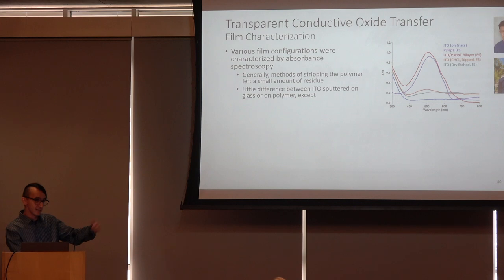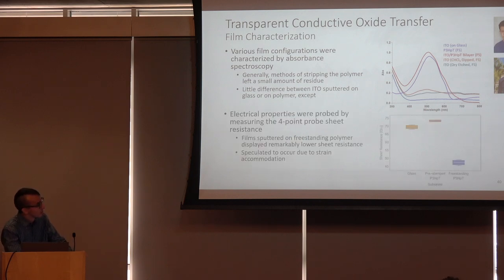And by etching away the polymer, you are increasing the optical impedance at the backside, and therefore you're going to be increasing the reflectance of these freestanding films. And just qualitatively speaking, looking at these freestanding etched ITO films, they are very shiny, much shinier than ITO on glass. That's about all I want to say about those UV-Vis scans.